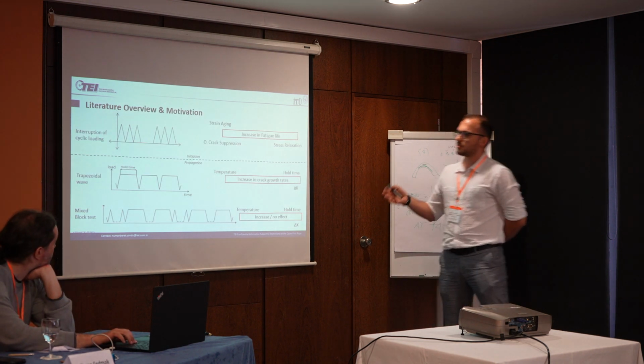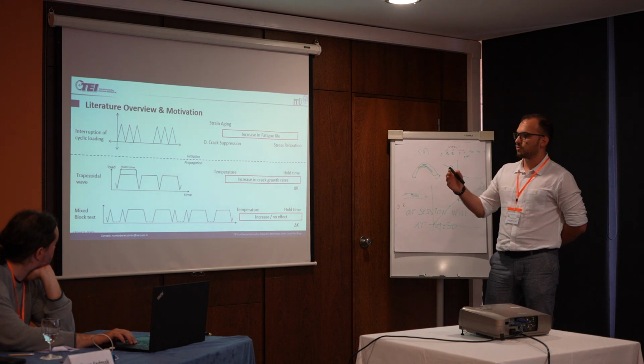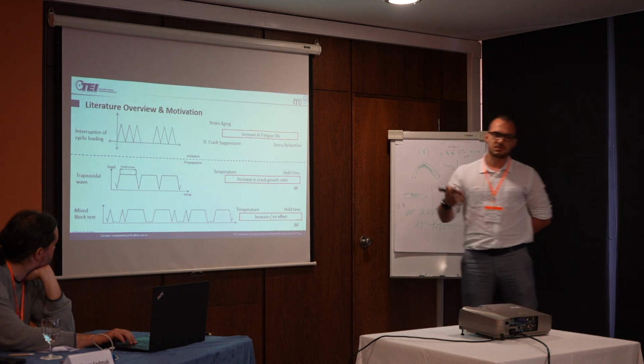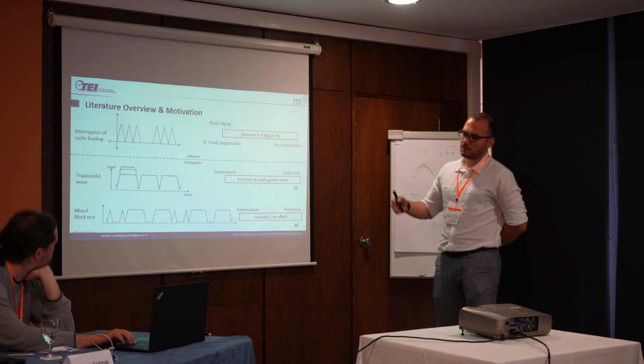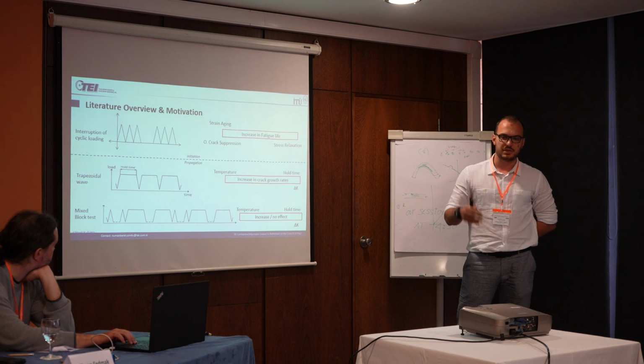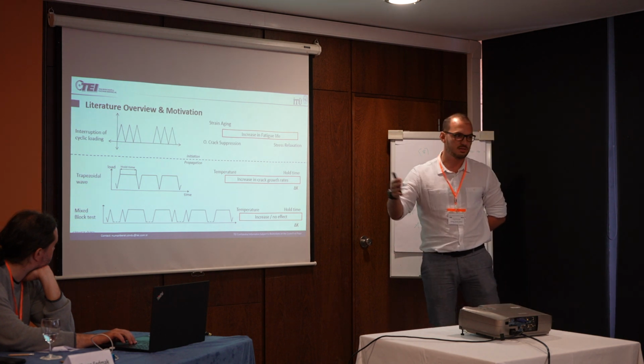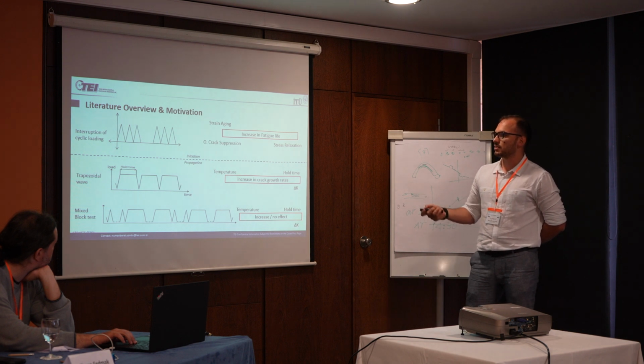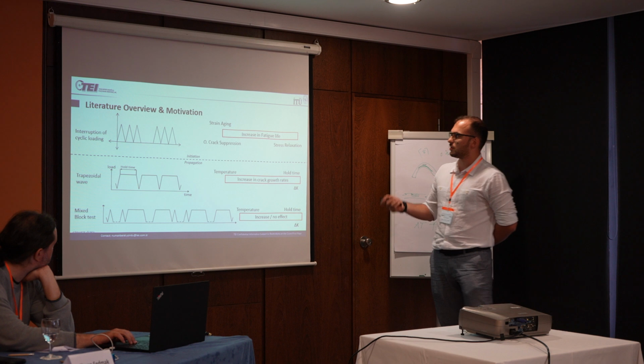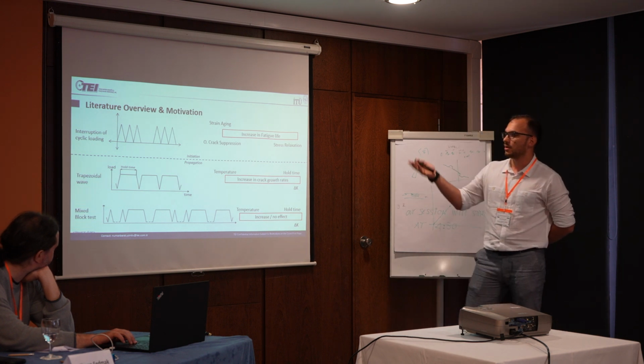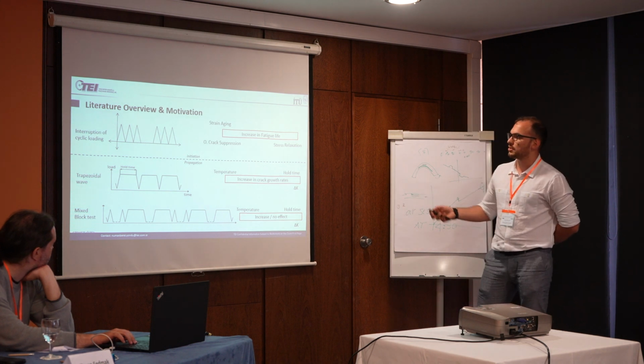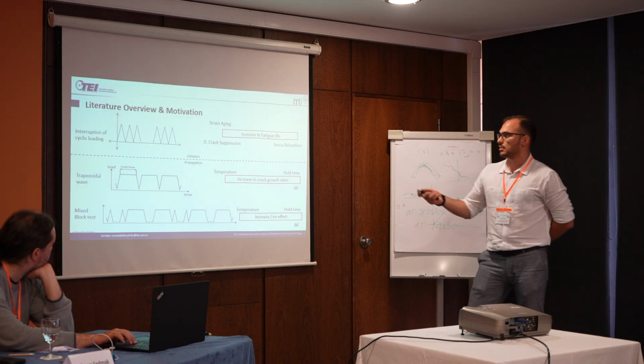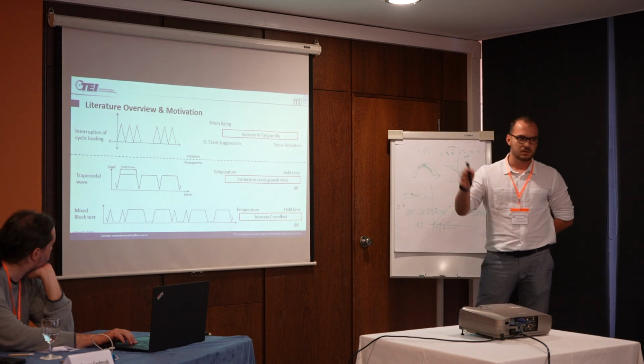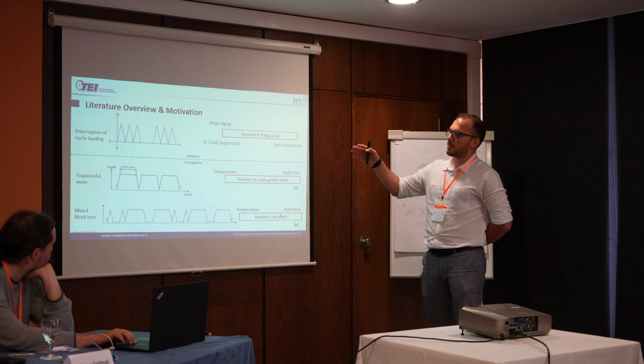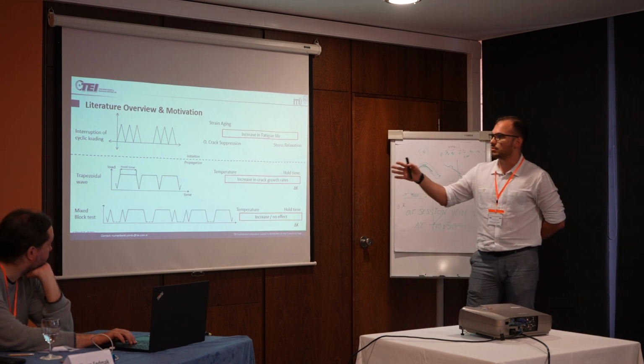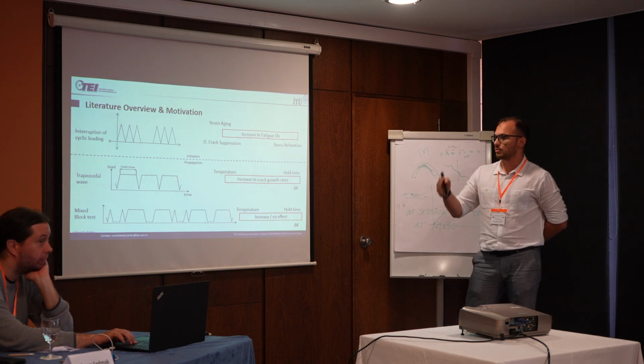In the literature, when we look at the early stage works and the recent works, we see different approaches. For example, in the early stages, we see the interruption of the fatigue loading, mainly made in the 1950s to 1980s, in which, in steels and also in nickel alloys, they observed an increase in fatigue life. That was because of strain aging, stress relaxation, and oxide-induced crack suppression. Strain aging and stress relaxation were mostly observed in steel materials, but in nickel alloys they observed oxide-induced crack suppression in terms of interrupting the fatigue loading.